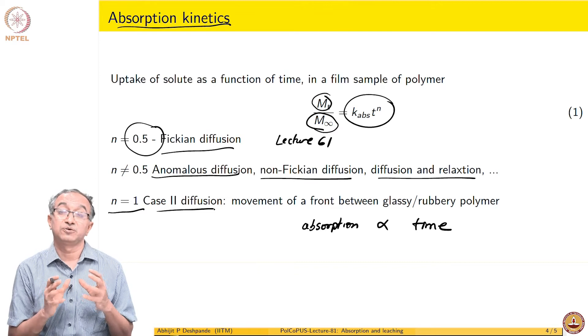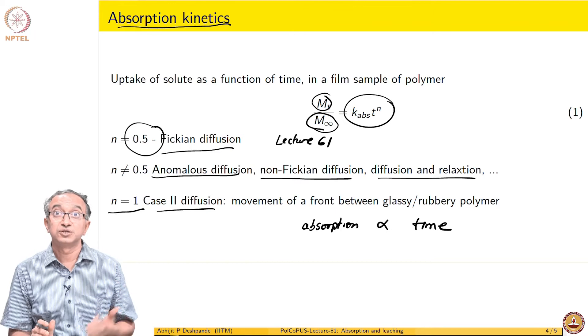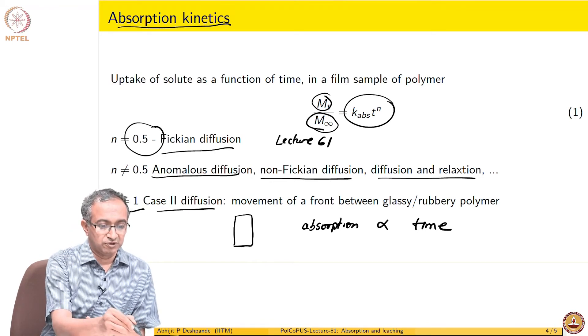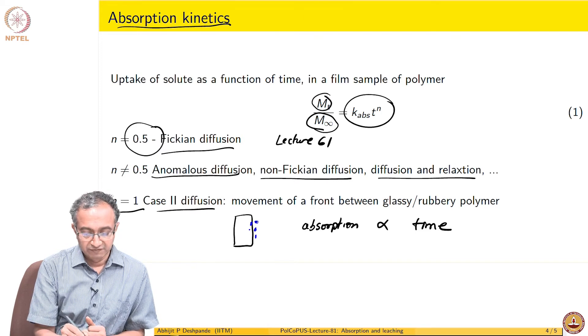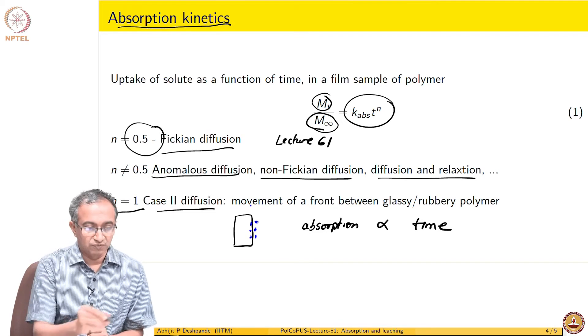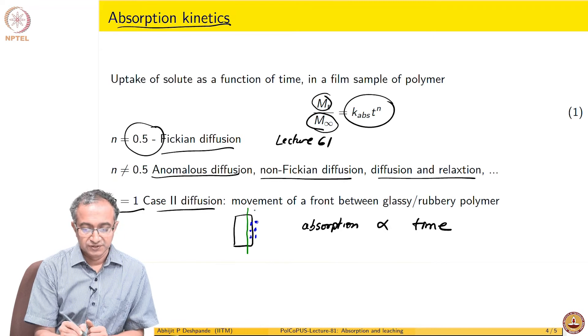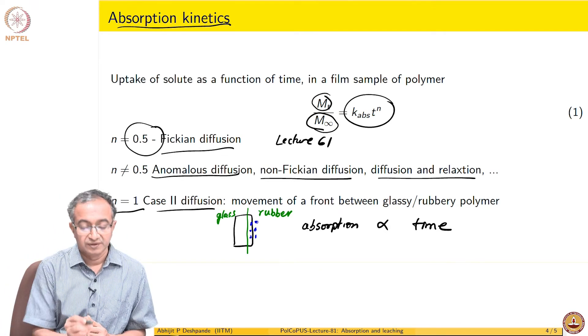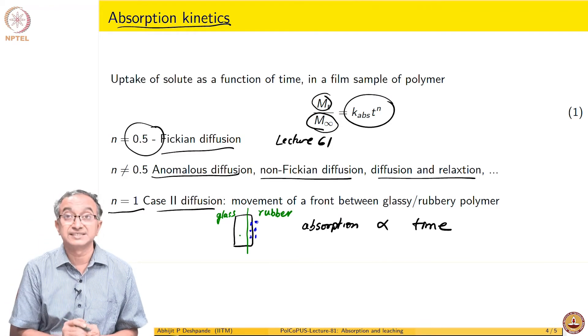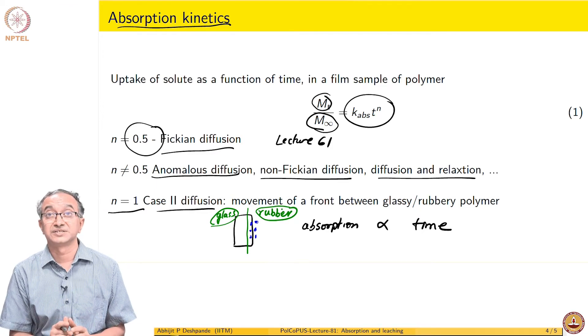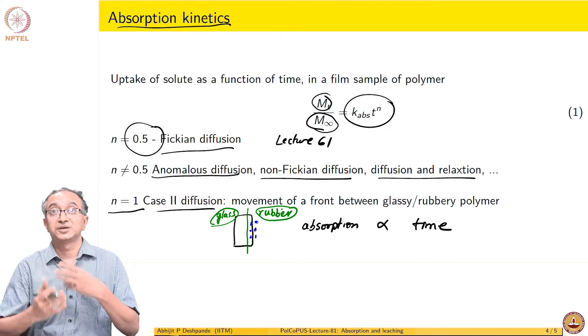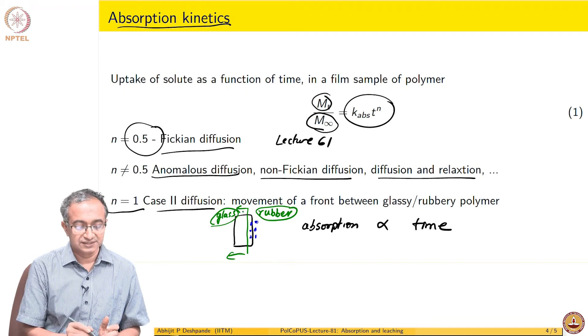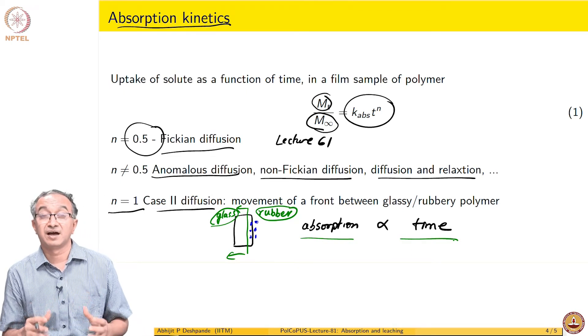One specific case observed quite often in polymers is where absorption is linearly proportional to time — this is called Case II diffusion. This is relevant when using solvents to recover or dissolve the polymer. What happens is: the polymer is in the glassy state, and when small molecules start coming in they get absorbed and plasticize the polymer. There is a front inside the material — on one side of the front the behavior is rubber-like with macromolecular segmental flexibility, while on the other side is the glassy state. The diffusion coefficient is very low in the glassy state and reasonably high in the rubbery state. This front keeps moving as small molecules keep coming in, get absorbed, modify macromolecular flexibility, and the absorption amount is proportional to time.